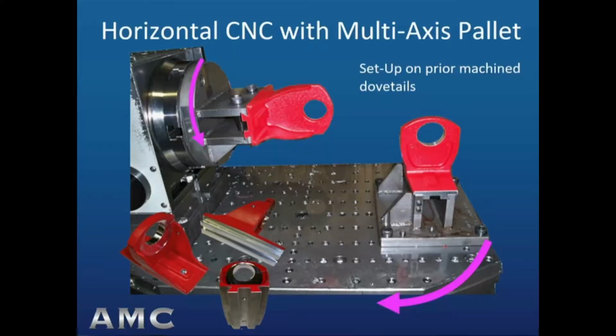Otherwise, as we will see in the horizontal CNC setups, the casting is set up on its machined dovetails, no longer using as-cast surfaces to control the machined features in the other 2 planes. Now, we can see how the machining of the casting in the other 2 planes is accomplished. Here, we have a setup for the horizontal CNC with a 2-axis pallet with 2 fixtures mounted on it.